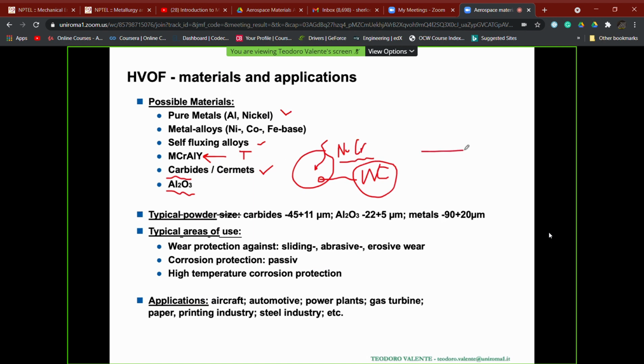Thus, the mechanism by which we can experience the splat and then form the coating is related to the presence of a melted phase, which is only the metallic phase. The area of use of this kind of technology is essentially to fabricate hard coatings, that is, wear resistant coatings, or corrosion protection coatings. I also mentioned high temperature corrosion protection because this is expected as one of the functions of a bond coat in thermal barrier coatings.